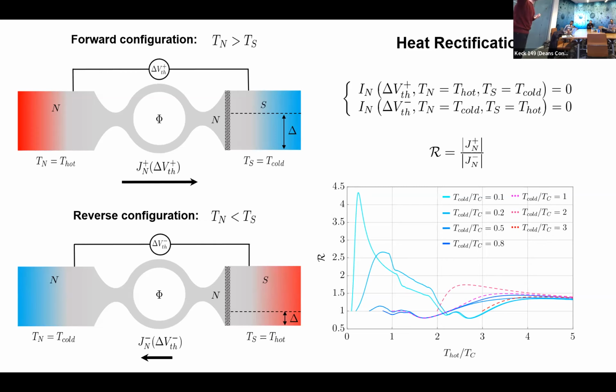So it's not a characteristic of our system. It's the way you have to do this experimentally, because you really have to counterbalance the system with that thermal voltage to make the current equal to 0. Otherwise, you have an electrical current. Yes, thank you for pointing out, because this is very well, and that's how you compute the Seebeck effect. The Seebeck effect is basically your thermal voltage divided by your temperature gradient at no current. Exactly. That's what you do in an experiment.